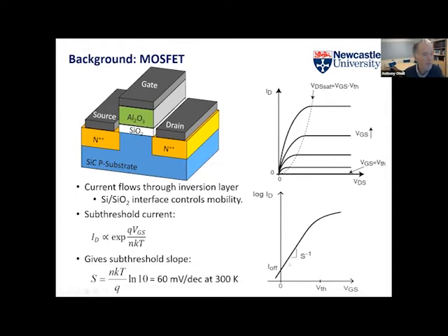As you increase the gate voltage, then you get an increase in the drain current, and that follows this kind of exponential behavior in gate voltage and then gradually rolls over. So the drain current can be conveniently described as being proportional to an exponential of the gate voltage multiplied by e over kT and some fiddle factor n, which takes into account things like defects in the material and defects particularly in the interface, which are going to affect the current.